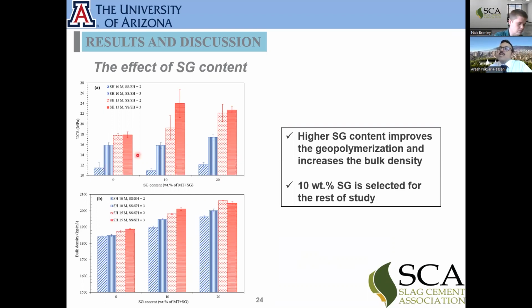When we are increasing the slag, the UCS is increasing. That's good. That means we can get more silica and alumina from the slag because the slag is a very highly reactive material. It experiences a high temperature in the smelting process. So it's already amorphous material, and you can easily take this silica and alumina out of the slag and produce this geopolymer. And also, because the slag is a heavy material, the specific gravity of the slag is much higher compared to the mine tailing, so the bulk unit density of the samples is also increasing. So how much slag should we use? Generally, we decided to keep this slag minimum 10%, because more slag is good, but the goal of this study was to try to recycle more of the mine tailings.